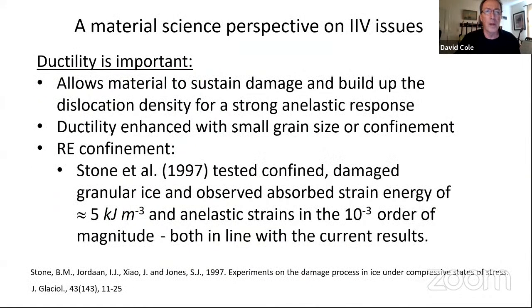A couple of quick points at the end. We did experiments with these ramp loading things on columnar freshwater ice. We saw nothing like what we saw with the granular ice, because that material is essentially more brittle than granular ice, and it would fail catastrophically before you could build up enough damage.